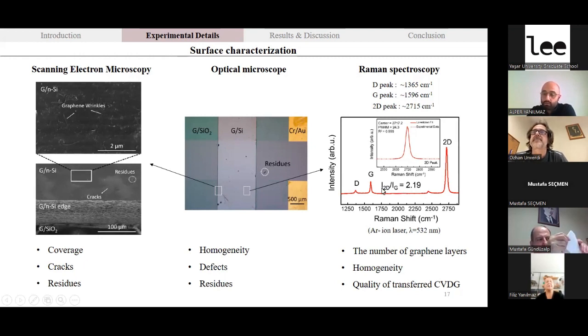The 2D peak is the second order peak of the D peak. The intensity ratio of the D peak with respect to the G peak gives the quality of the graphene. By the way, the homogeneity, the number of layers, and the quality of the transferred graphene can be easily characterized using Raman spectroscopy.